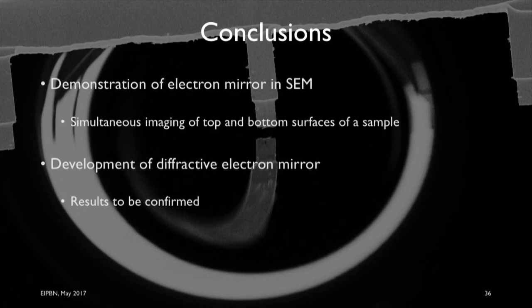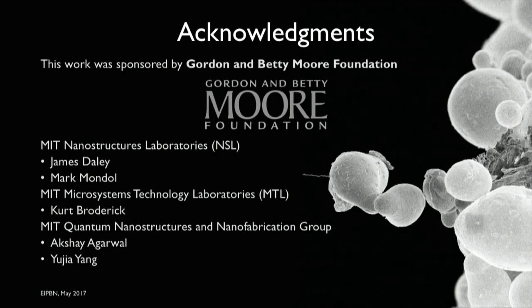So in conclusion, we've demonstrated electron mirrors in an SEM. We've demonstrated simultaneous imaging of the top and bottom surface of a sample. We've developed and fabricated diffractive electron mirrors. And we have some preliminary results of diffractive electron mirrors having multiple images of the bottom surface of the sample at the same time. But these results are still to be confirmed. Thank you for your attention.